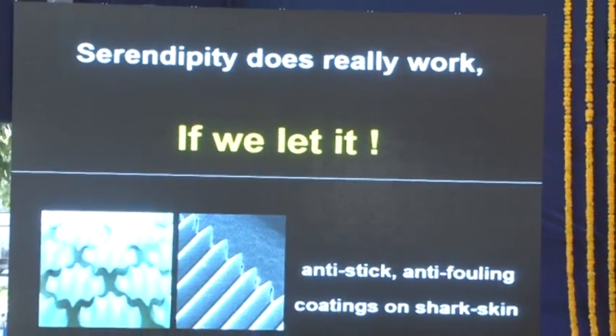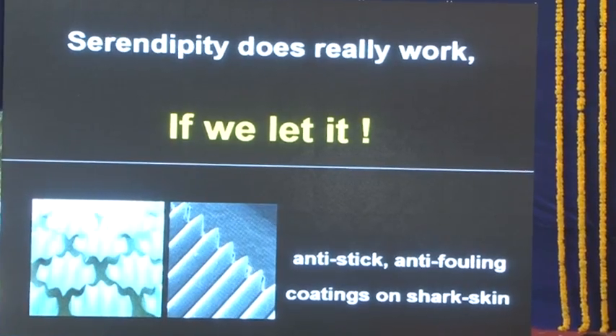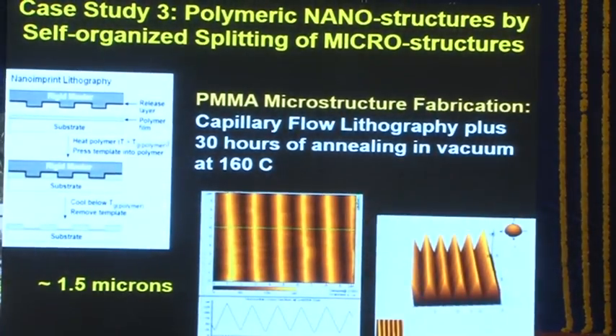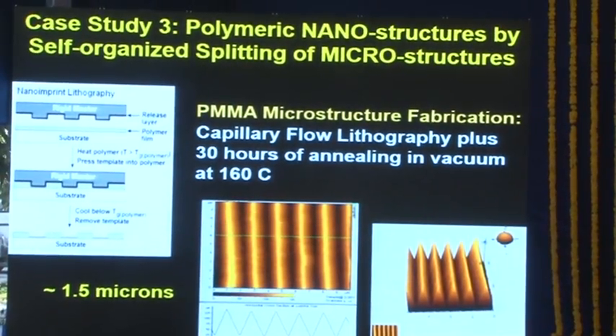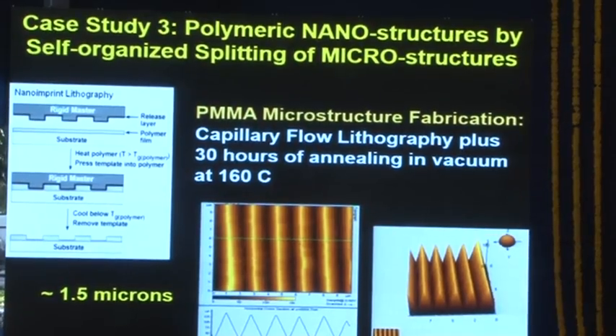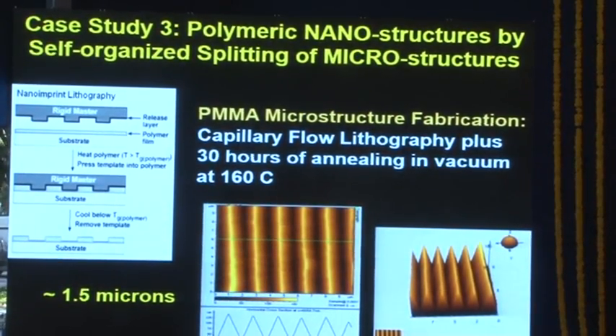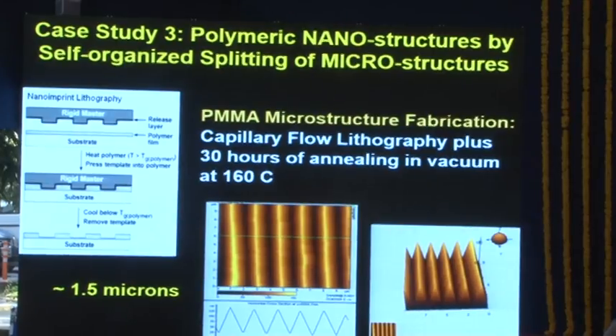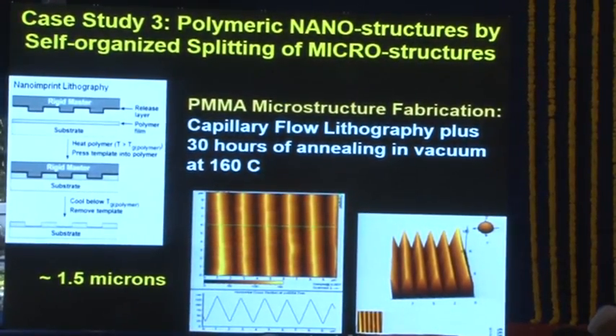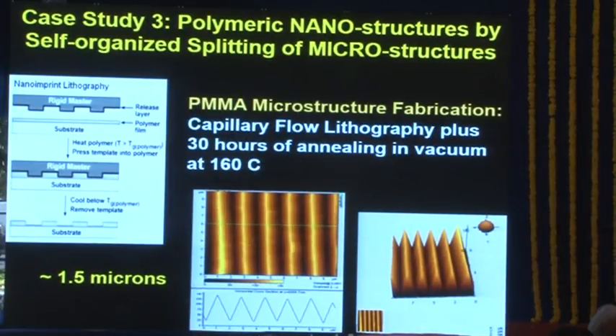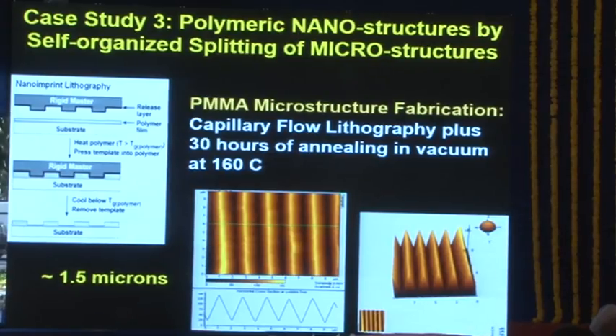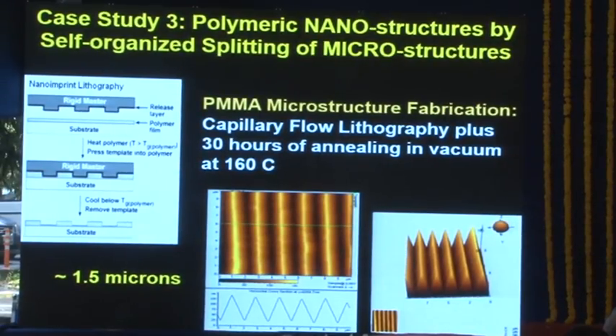And how do you do that? Well, you do that by making a stamp and then pressing it on a block or a film of polymer. Soften the polymer, then apply pressure, and just replicate these features. So that's the usual way that one does it. Here you see there is a stamp going down on a polymer surface, and then it would create this microstructure that you see there, which is triangular pyramids repeated over the entire surface, which is what you see in the right-hand corner there. So you make that structure, which is fairly straightforward. It's a well-known technique of micro-nano fabrication, stamping. So you do the stamping, and you create the microstructure.